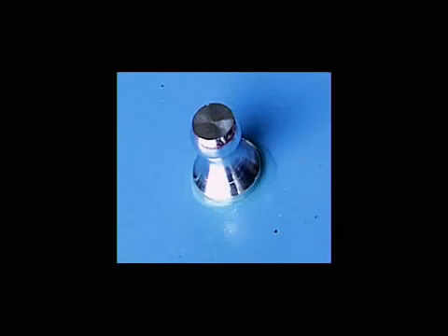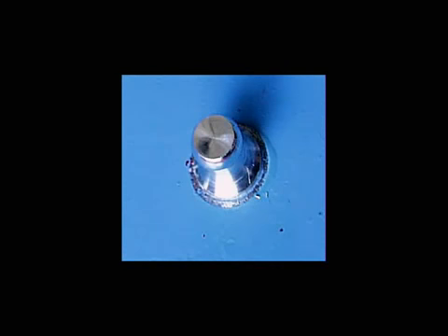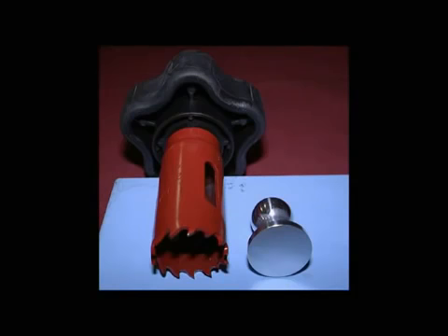After proper cure time, the operator must decide whether or not to cut the coating around the dolly. As a minimum, any excess epoxy that appears during the curing process should be carefully cut away to prevent an increase in the pull-off area. A common method is the use of a cutting tool with an inside diameter matching the dolly size.